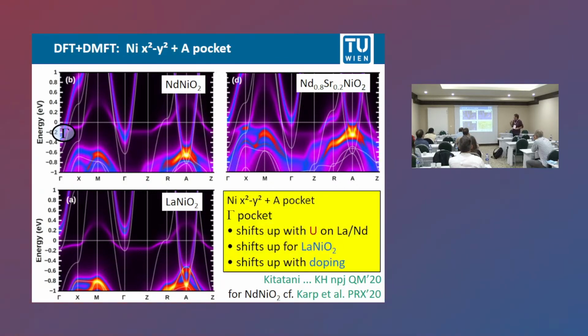So here is, by the way, the z² orbital, still below the Fermi energy. And let's now, based on these ab initio calculations with all d orbitals included, get at a simple description. And the simple description is, okay, I have this x²−y² orbital, an A pocket, in some compounds at low doping, possibly also a gamma pocket. But these two are there all the time, also in the superconducting regime. So these are the relevant orbitals in our calculation.